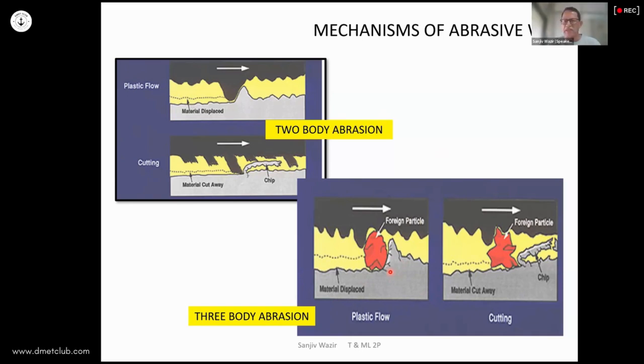So then in the third, three-body wear, one more important parameter which plays a role is the thickness of the oil film versus the thickness of the dirt, the grit or the hard material, right? So for example, the oil film was 50 micron here, and the dirt was 2 micron, 5 micron. That piece of dirt is likely to pass through without causing wear. So we are not really worried about that. What is going to be worrying us is a grit size of roughly 40, 50, 60, 70 micron. That would be really dangerous. That would rub against the surface and cause wear.